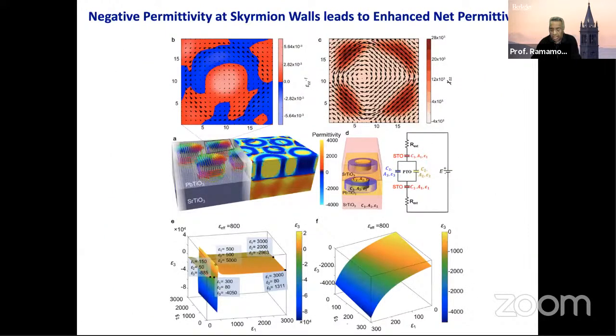Let me pass on this because this is telling you the same thing as a static picture. Our ab initio colleagues told us, hey, look, when we do ab initio calculation for a single skyrmion, this is the susceptibility of the system. Chi is measuring the susceptibility. And they said right around the periphery of the skyrmion, the belt part of the skyrmion, the susceptibility of the system is very large. And typically when you have large susceptibility, you're thinking, okay, there's going to be a phase transition. So it's a very large susceptibility right around the periphery.